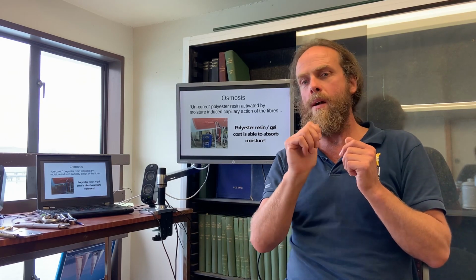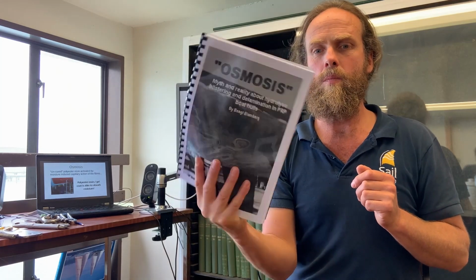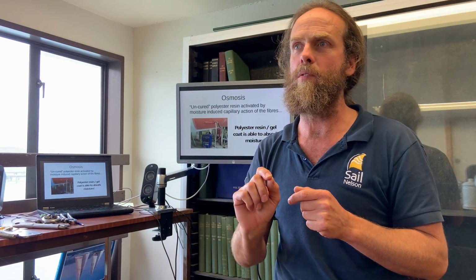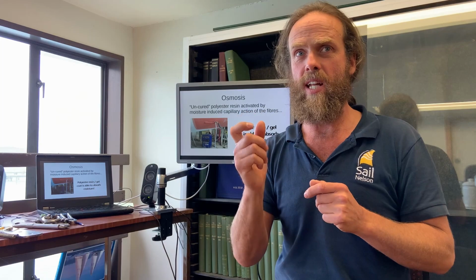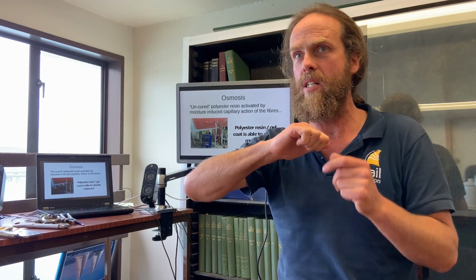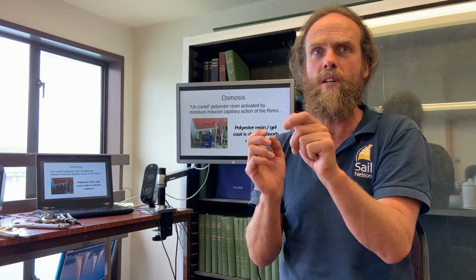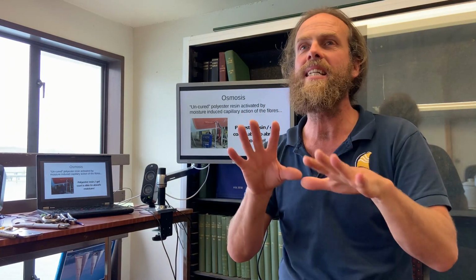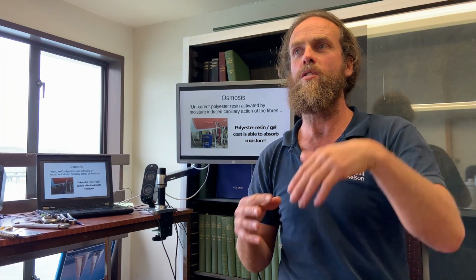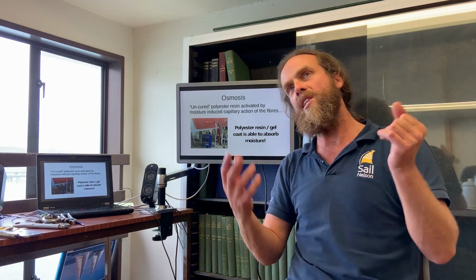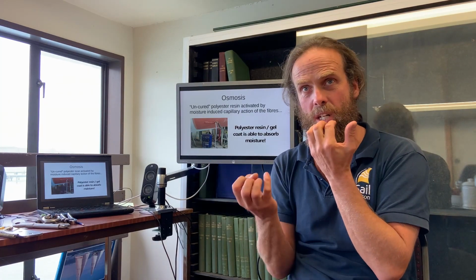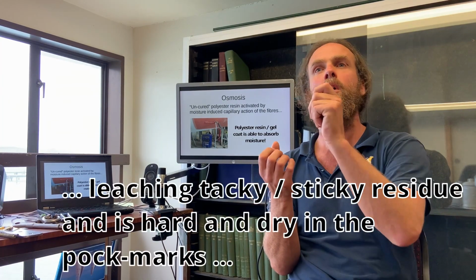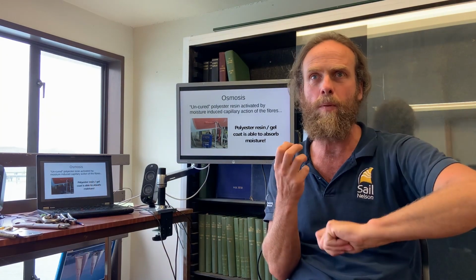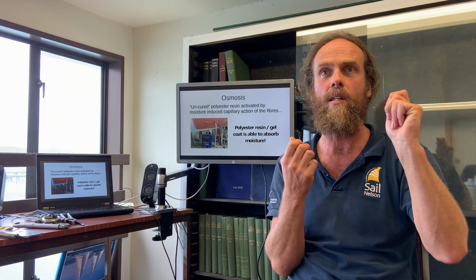The advice I then received, which is concurrent with this chap's work, is that we want to flush the acid out of those pock marks. So with acetone in a syringe, we're literally going to go around and squirt acetone and flush this, scrub it with a little stiff brush in there, do whatever it takes, and repeatedly over a week or two, you're flushing this acid out until there's no residue turning up at all. And then very simply, he says, once that's stopped leaching any kind of nasty out of there, we're then going to epoxy repair, probably with micro balloons or something, back into those divots that we've created.